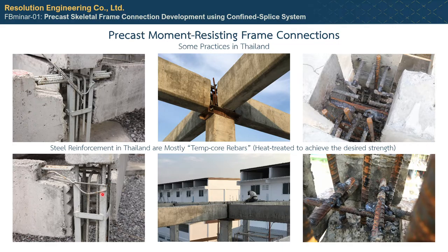But I'll get my technician to try a few specimen tests. The quality control of the welds is very important. The penetration depth of the weld bead is very important. You need the large welding electrode to get good penetration into the rebar splice. Otherwise, it is just the covering, but the core is not sticking. I tested using UTM, and I found that in the middle it's not touching. We don't see the full penetration welding.